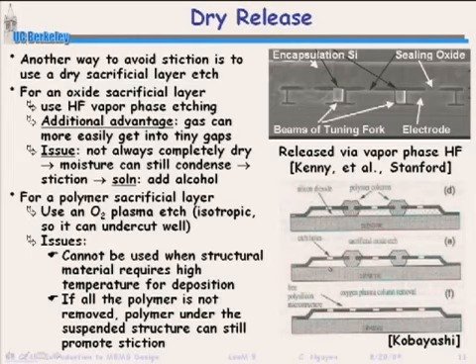There are some drawbacks with this here, is that if the polymer is not completely removed, then, right, it's kind of like glue almost, right? If your structure comes down, there's still polymer there, it can make your structure stick to itself. Okay, so it's not a perfect process either. Vapor phase HF is pretty good. Vapor phase HF, supercritical CO2 drying, those are good ways to solve this problem.